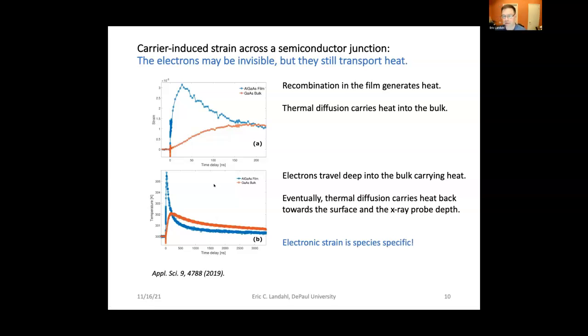But then something interesting happens, which is that at longer time scales, now here out to 3 microseconds or more, we've noticed this is a very robust effect that this substrate is warmer. And that is because those electrons have gone in, are heating very deep in, and the heat is actually moving back towards the junction and towards the surface, the area which is probed by the X-rays. So this indicates that we're not fooling ourselves. The electrons are in fact reaching into the bulk of the material. We just don't see their effect in strain until they have thermalized.